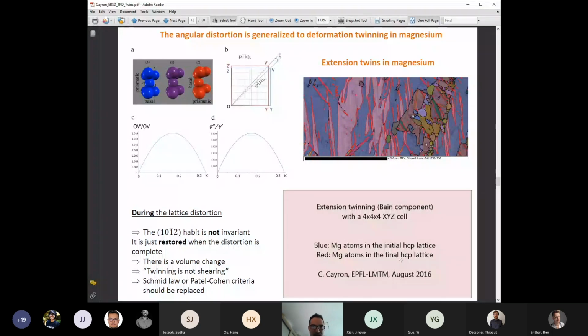For example, if I look at extension twins in magnesium, here it's an EBSD map. You see these red grain boundaries are actually the boundaries representing 86 degree misorientation rotation around the A-axis, I think. So if you look at these twins, you can make exactly the same thing. You can look at the atoms in the HCP structure of magnesium, look after twinning where the atoms are, and make a continuous path between the two structures.